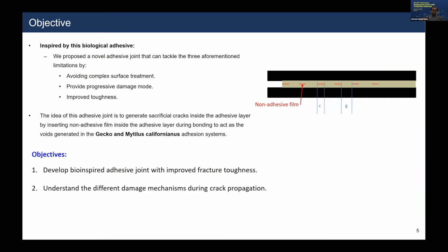So inspired by this biological adhesion system, we propose a novel adhesive joint that can tackle three limitations: avoid complex surface treatment, provide progressive damage mode, and improve toughness. The idea of this adhesive joint is to generate sacrificial cracks, which are marked in red here, inside the adhesive layer by inserting non-adhesive film inside the adhesive layer during bonding, to act as the voids generated in the Mytilus californianus, and also another example which I didn't show here, the Gecko. So the objective of this work is to develop a bio-inspired adhesive joint with improved fracture toughness and understand the different damage mechanisms during crack propagation.